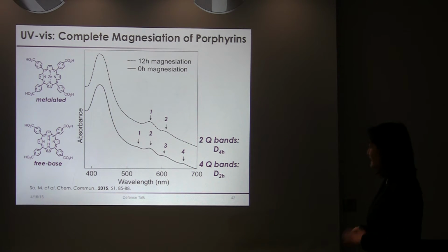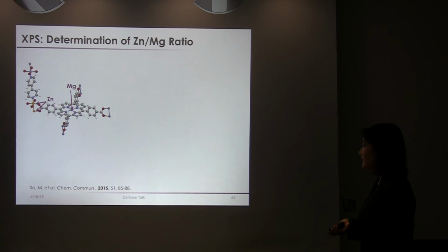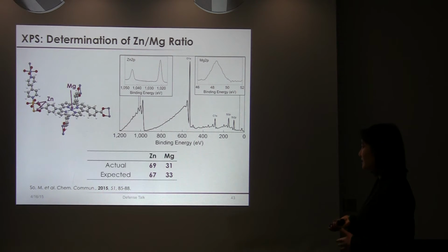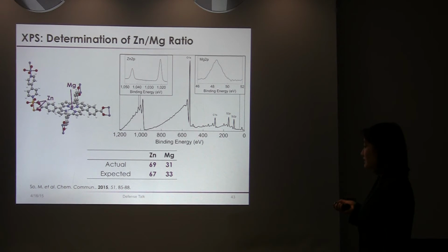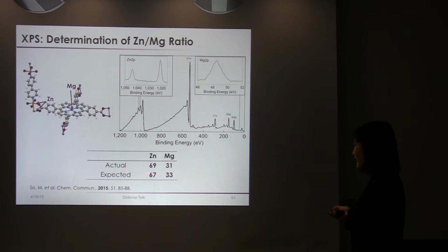But in any case, I just wanted to have a quick check of whether there was metallation that occurred, but I wasn't sure what kind of metal content was in the film. So I had to do XPS, and in this case, I expected there to be a 2-to-1 ratio of zinc to magnesium ions in the MOF film. And so after integrating the peaks, I noted that there was indeed a 2-to-1 zinc to magnesium ratio in a post-magnesiated MOF film.